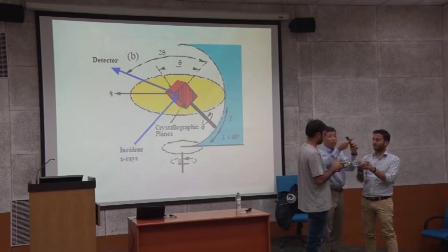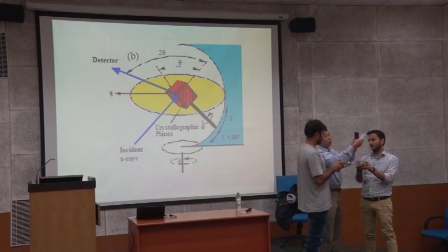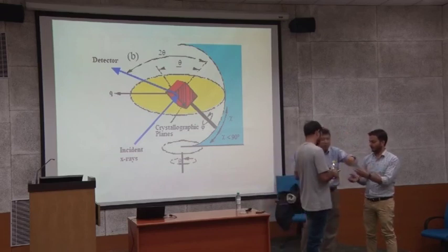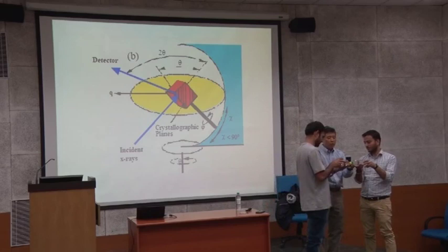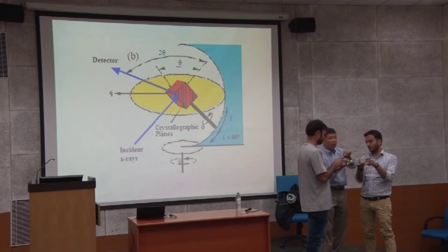Okay? Then once you have this, the peak is not everywhere. So you want to access this, after moving this, then I have to spin this one. Spinning is phi. Phi can access this. So again, you have this one. I lock this, but you can also spin this. This is phi. Phi goes 360 degrees, but this one, chi, can only go 90. This one chi, this one phi,